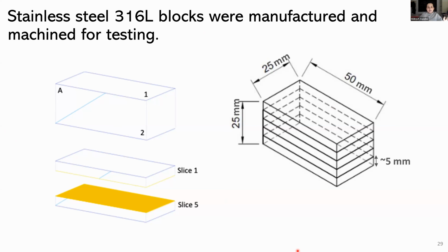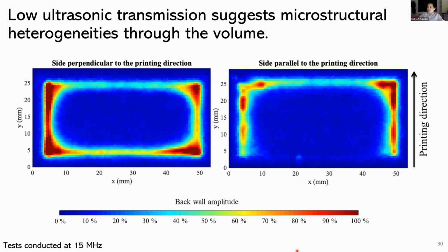This is what the company that provided the samples said was their optimized process. Surely this is going to work smoothly, and these are going to be samples that are rather easy to analyze. But the reality was that once we started doing that testing, we actually got quite low transmission through the center of the samples and much higher transmission around the edges. So this was already suggesting that the samples weren't as simple as we anticipated. It ended up being a pretty interesting analysis of what resulted from these samples. So it was all good in the end, but this was our first indication of, oh wait, maybe these samples are not responding the way that the manufacturer thinks they are.